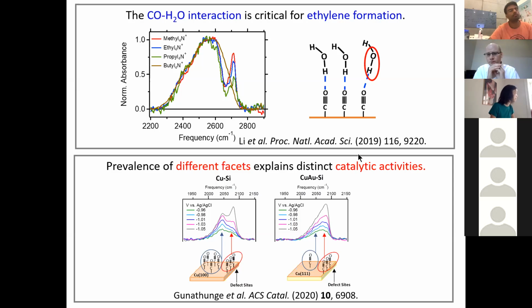I'm sorry, if I can just add something, because I was part of that paper too, so I feel like I should say something about that. What we found with Bell is actually that the cesium ions, at least when we consider the hydrated size, are actually smaller. So it's actually quite consistent. Lithium actually has a larger hydrated ion size, and so we can use the same kind of field picture. Right, and also I should point out the sizes of the cations that I mentioned here were derived from thermodynamic quantities, from the partial molar volumes of these cations. So I'm not sure how to think about it, but I believe the numbers that I cited will to some extent include some type of hydration.